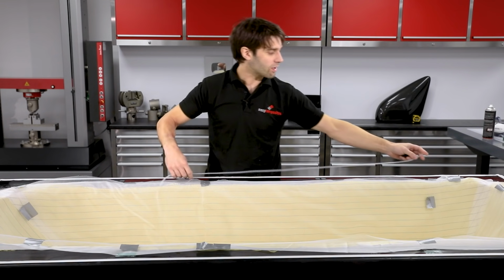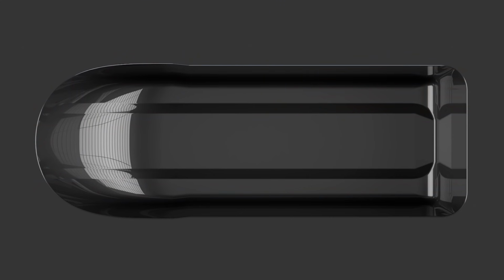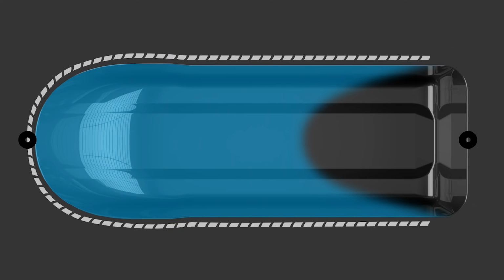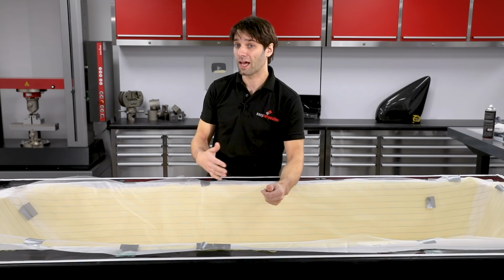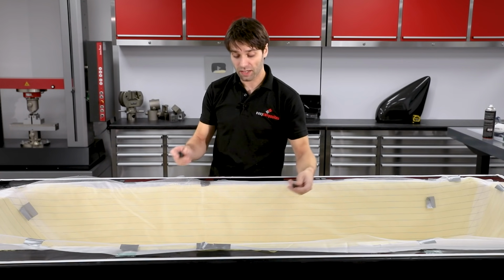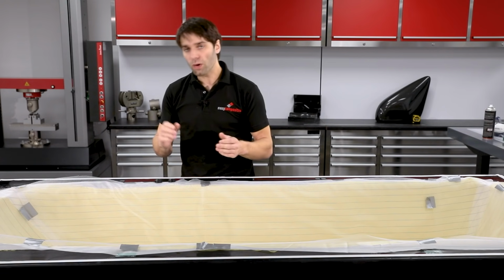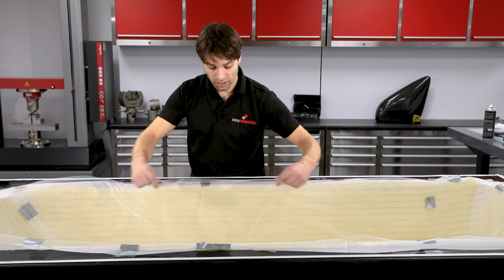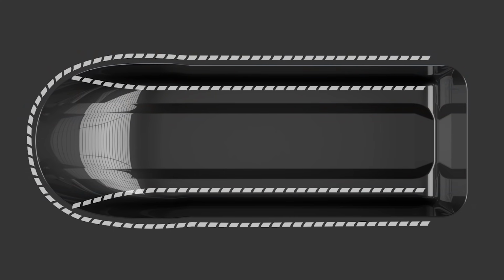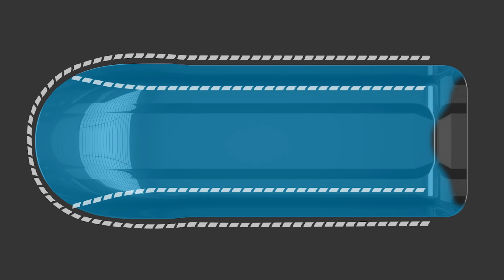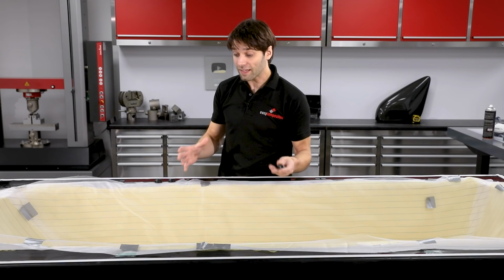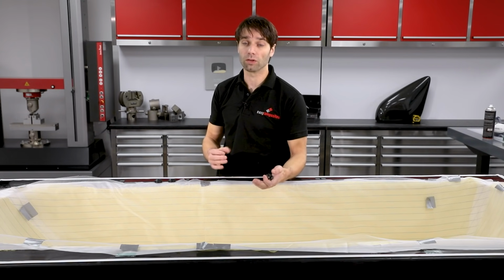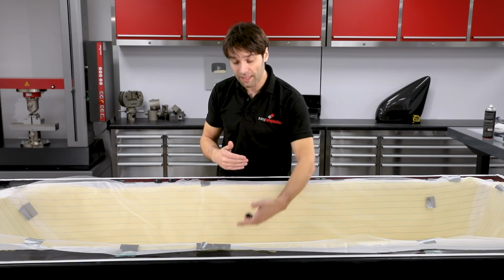Well, if we ran the spiral not only down the side here, but we also ran around in a U shape, right around the perimeter, then we're only asking the resin to flow from the spiral down half of that distance. So now we're 4 times quicker still. So at that point, we're probably looking at something like 30 minutes. It depends. The main restriction in that situation is going to start to be the connectors. We can go even faster still by running additional spirals down the centre, another one here, and then we are only asking it to flow for around about 250-300 millimetres. And that's going to start bringing our infusion times down into the minutes. So the main thing you're looking to do is reduce the distance it has to flow from a spiral. A rule of thumb on that is 500 millimetres, so half a metre of flow distance.